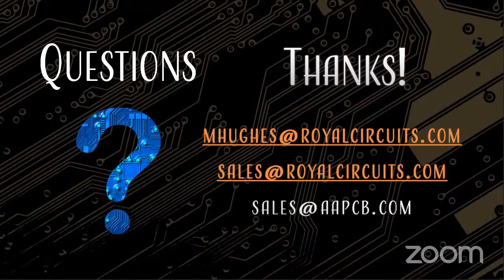Other issues are registration, right? The stuff that you send us isn't what we etch. We have to modify, stretch and shrink things in certain areas. And then we've got to get everything aligned when you squish it all together. It's really hard to do. So for cap construction, your yield is always going to go down. Foil construction, right? We can throw your board into an X-ray machine and we can visibly see what's happening on a lower layer so that we know that we're lined up on the layer above it. So we've got much more control over foil construction than we do with the cap.